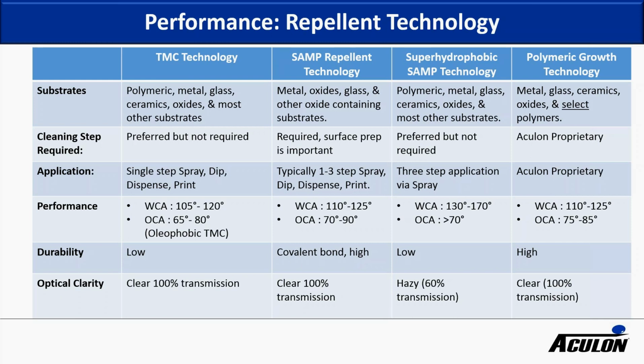The superhydrophobic SAMP technology is basically an extension of the SAMP, where we build up some roughness with an organometallic. That roughness introduces some haze to the surface, and it's also quite brittle. So mainly this is used for fluidic applications where the mechanical durability requirements are pretty low. But you do get a pretty substantial performance boost in water contact angles, above 130 up to 170. Oil contact angles are very high, and this is usually done in a 3-step process where we spray the organometallic twice and then spray the SAMP solution.